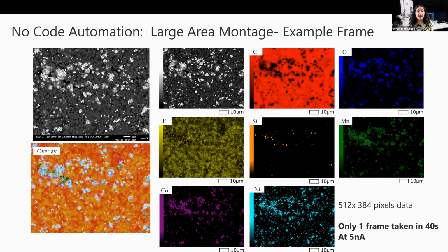Shown here is the EDS map analysis data for just one of the montaged frames. A single pass at 512 by 384 pixel resolution was completed in just 40 seconds. Despite the short acquisition time, the signal quality and detail are excellent because we used 5 nanoamps of beam current. In total, 16 frames of this quality were acquired automatically and unattended during the montage process.